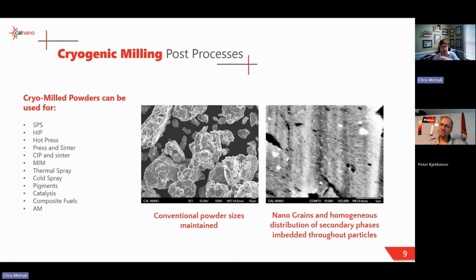So we're always going to compress them, and then we're going to sinter them. So we form solid state alloys in the powder form. And that also applies to adding those ceramic particles. If you're making metal matrix composite or oxide dispersion strengthened material systems, often the ceramic that you're putting in there is not going to be the same density as the metal matrix around it. It's either going to be more dense or less dense.